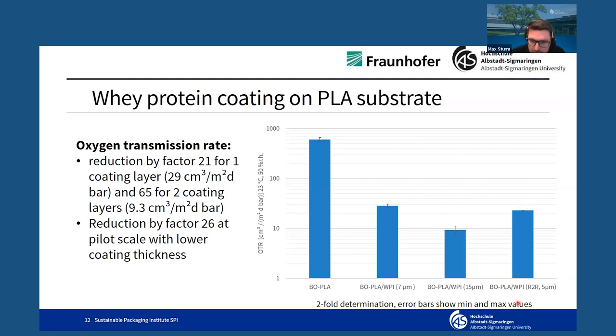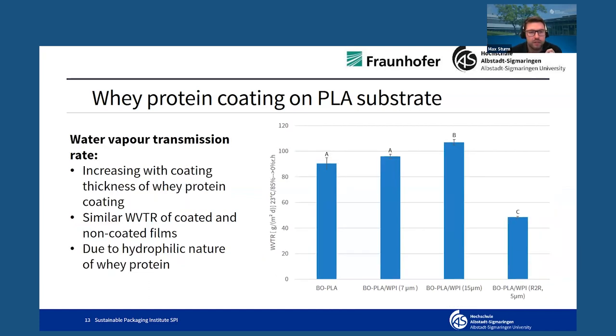In the results you can see here, there's even better results than on the lab scale with 2 micrometer thinner coating even. So comparing this to this, this is due to the more homogeneous coating and due to the different coating processes, as I mentioned before. Next up, we also analyzed the water vapor transmission rates of the coated PLA films. Here you can see an increasing trend with increasing coating thickness. This is due to the hydrophilic nature of the whey protein itself. So this allows for a higher permeability against water vapor.